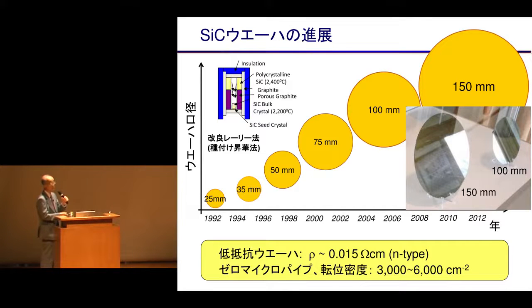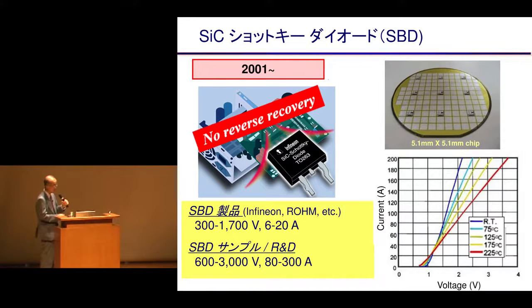Now in devices, on top of the 4-inch wafer, devices are being produced. Now with the strong request for 6-inch, that's 150 millimeter diameter, it is tried. That is 150 millimeter, 6-inch, and 4-inch. Different from the silicon, it's not dissolved, so the sublimation method is used. So the seed would be grown. That's the method for the silicon carbide. Therefore, crystallization properties are quite different from the silicon.